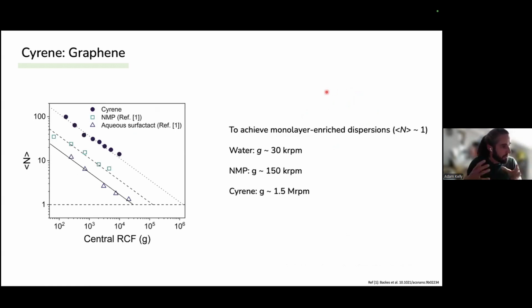So if we want to achieve a monolayer enriched dispersion where the average distribution is approximately 1 for layer number, for centrifuging in water, we would need a G-force of about 30 kRPM. For NMP, we would need a G-force of about, say, 150 kRPM. And for Cyrene, we would need to go up to about 1.5 million RPM. So as far as I know, these centrifuges you only get in molecular biology labs. And generally, the volumes that you put in here are way too small to be doing anything like creating inks.